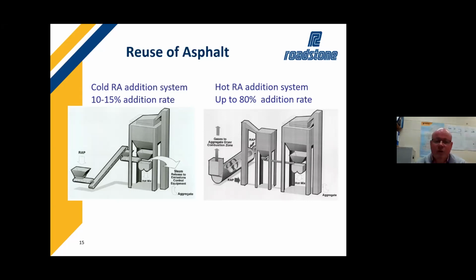So you saw that dryer drum that we had for drying the aggregates in the original plant schematic. Well, this has a second dryer drum for drying the RAP, and the RAP comes through the drum, reaches an elevated temperature. It's then moved to a hopper right beside the mixer, and then it's used in higher amounts in the mixer. So with cold RAP, reclaimed asphalt, I've got 10 to 15% there. I think you can get as high as 25% at times if your moisture content is low. Your hot RAP system, we've seen levels as high as 80%, and I believe Benninghoven and Amman and a few other asphalt plant producers are talking about 100% recycling in their newer facilities.